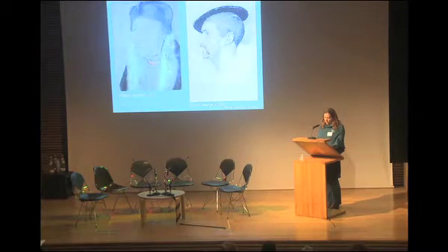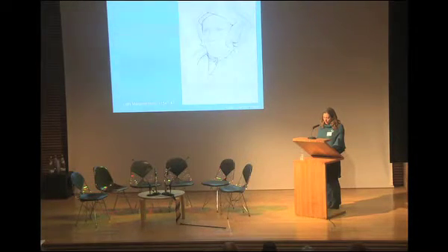Where there is a predominant use of chalk, contours can be subtle while still apparent, as in the case of William Warham, seen here on the left, or more emphatic, as in the case of the drawing of Simon George on the right, where black aqueous media is a prominent material. The exaggerated emphasis of contours in some cases is not always originally intentional, but is a consequence of tracing for transfer or abrasion of surrounding areas, further accentuating the black media, seen here with Lady Margaret Butts, for example.